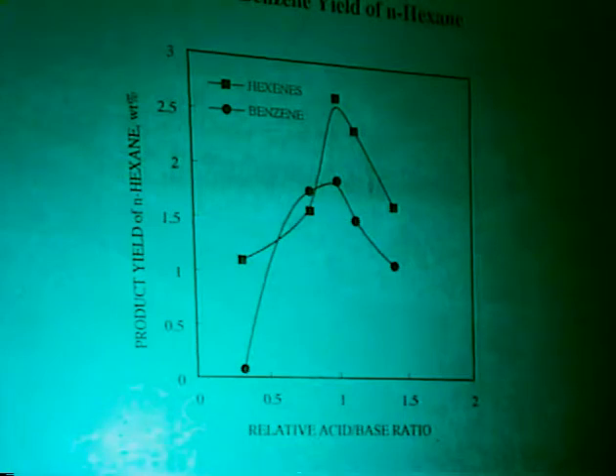Using normal hexane, we see the same result. The 1-hexene yield and benzene yield both show a volcano shift with the acid-to-base ratio, confirming that the dehydrogenation and dehydrocyclization products of normal hexane require the paired acid-base site as the active site on the catalyst.